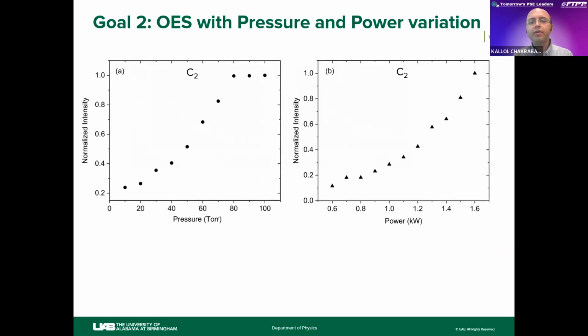Next, we focus on the C2 peak because it is a very important growth species for carbon-rich BCN deposition. As you can see, when we keep power constant and increase the pressure, the C2 peak intensity increases and saturates at some point. And when we keep pressure constant and increase the power, our C2 peak intensity also increases.